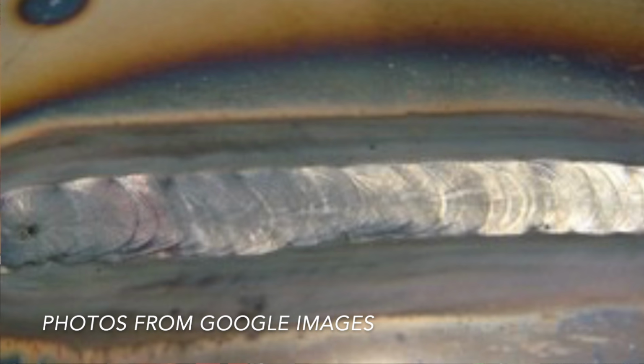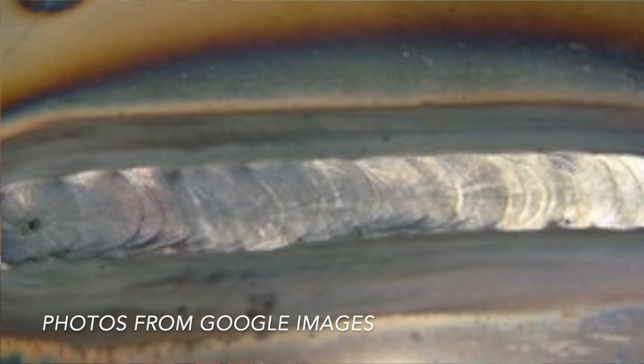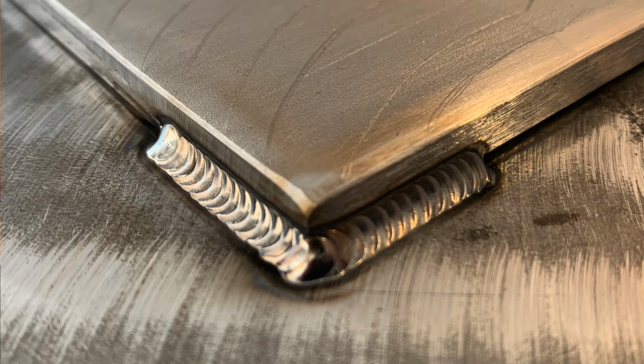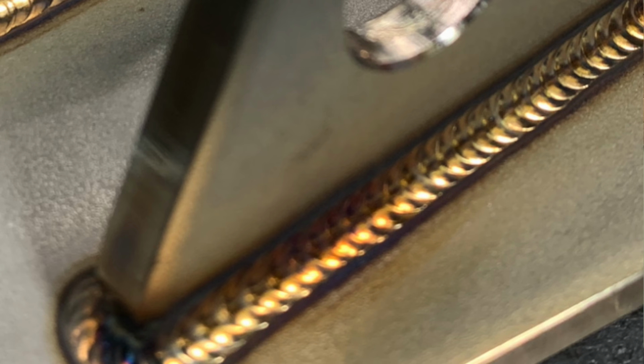Anytime you see weld areas that look very gray, kind of crusty, a little bit cloudy, it basically means that the weld material has overheated a little bit. And because it was so hot, the gas coverage coming out of your torch was not enough to keep that safe from being oxidized. So what you're looking for is a weld something like this. These are some welds that I've done where you see a lot of gold color. Basically a gold or straw color is going to be the most, quote unquote, clean or oxide free type of welding. A little bit of color is pretty common as well.